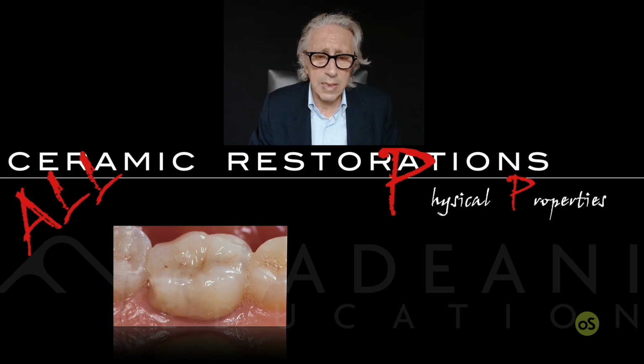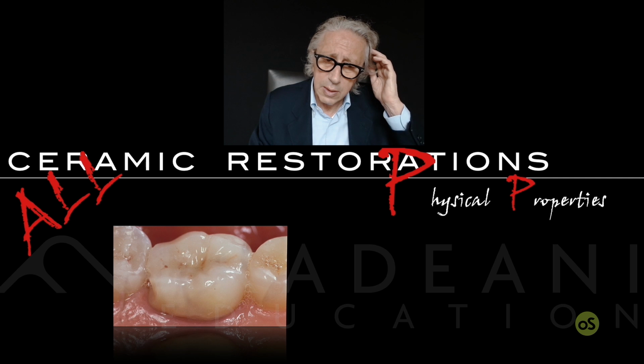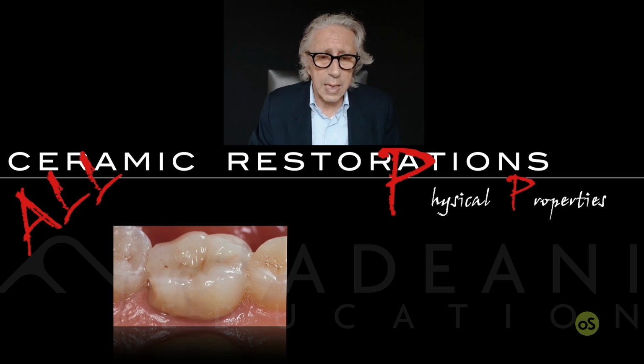That is a kind of little chipping that we have in the layering process. Today, I want to anticipate to you, all the posterior area in our office, we do just monolithic material, both zirconia and lithium disilicate. So in this case, it was layered, and the layering was chipping over there. But the coping that is quite strong underneath remains intact, like, for example, the metal ceramic work.